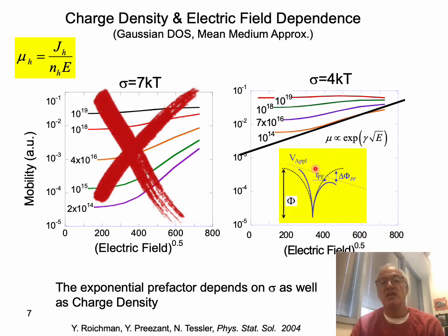And this is really, if you like, what is commonly accepted, that the reason that the mobility is increasing in this manner is very much similar to the Poole-Frenkel effect. And what we are actually doing in the sample, we are lowering the height of the sites that are farther in the direction of the electric field.